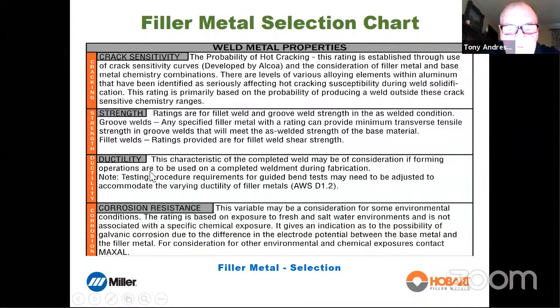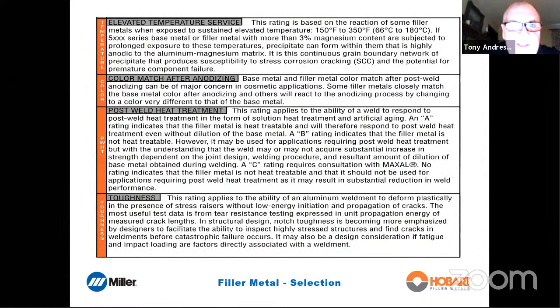Ductility, yeah, big difference. Typically, the 4000 series lack ductility. They have lower ductility than the 5000 series. Corrosion resistance, absolutely. There are differences in filler alloys, and we have ratings for them. Elevated temperature service, critical. There are only certain filler alloys that can be used at temperatures above 150 degrees Fahrenheit. If you choose the wrong one, you're going to get into stress corrosion cracking problems. Color match after anodizing, big deal. If you're going to anodize a cosmetic component and you use the wrong filler alloy, all the welds are going to go black. Post-weld heat treatment, yeah. Some filler alloys will respond favorably to post-weld heat treatment. Others will not. In fact, it would be a bad thing to use some filler alloys and then post-weld heat treat. And then toughness, certainly. There are differences in toughness between the filler alloys. So all of these ratings are covered in the filler alloy selection chart.